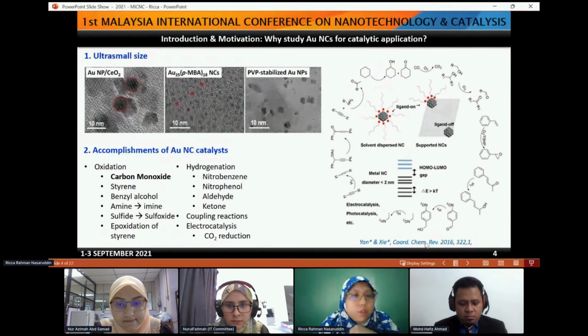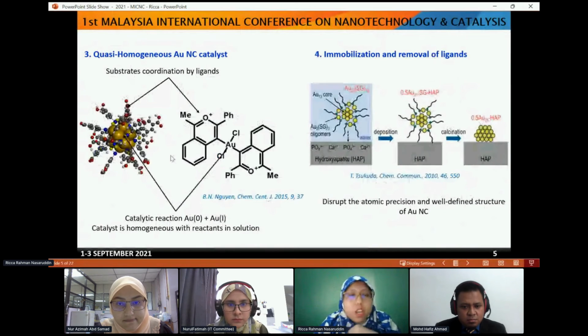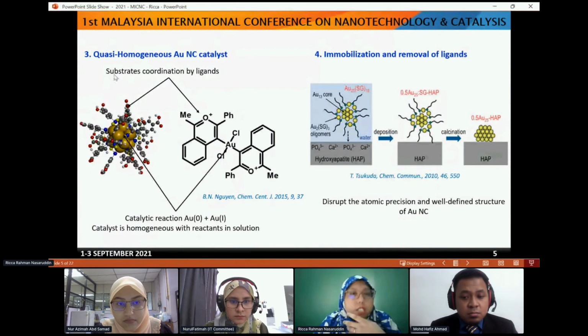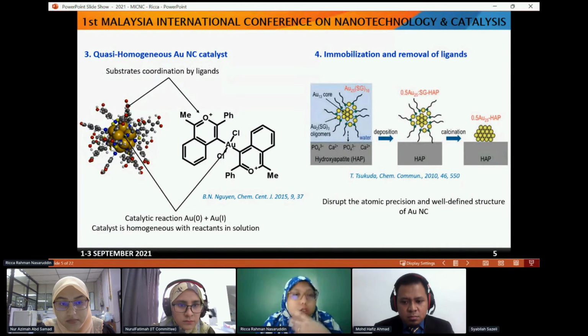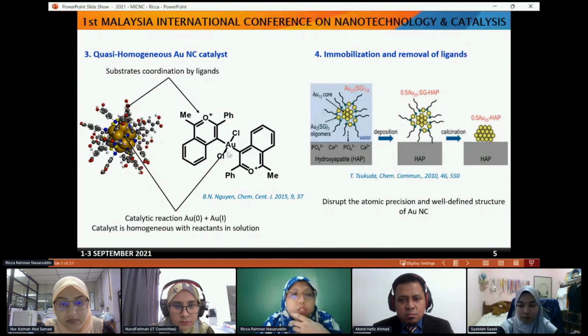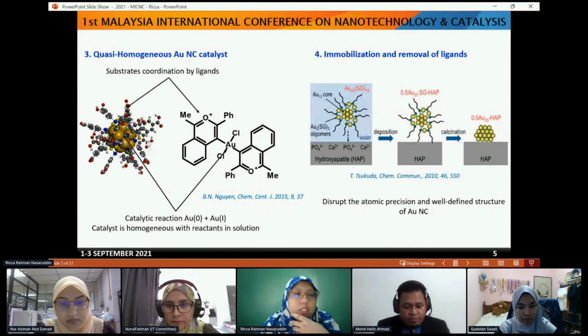In terms of the accomplishments of gold nanocluster for catalysis, there are several chemical reactions published in this Coordination Chemistry Reviews. You can do oxidations, hydrogenations, coupling reactions, and also electrocatalysis. Another important feature of this ligand-protected gold nanocluster is that it can behave like a homogeneous catalyst. It is a quasi-homogeneous gold nanocluster catalyst, where the core is your active gold. Like in homogeneous catalysis, you have a gold atom complexed with the ligand. But here, you have a staple motif as the protecting shell, and then you also have the ligand.